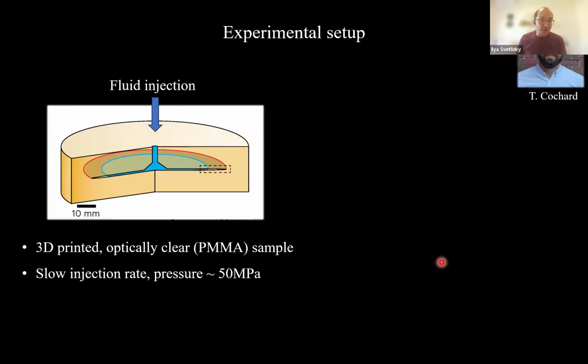Then, by injecting the fluid at very, very slow rates, it takes a couple of minutes to fill up the whole sample. And the crack will initiate, or the crack will start running, once the pressure reaches something like 50 megapascal. Now, the control parameter is the viscosity of the fluid that we are using, somewhere between water, 1 centipoise, to almost 800 centipoise.